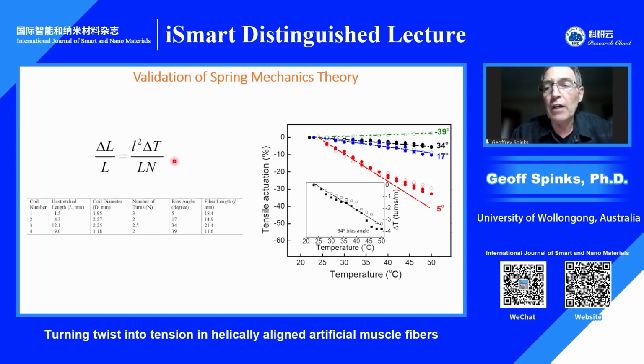And you can see there's really good agreement between the spring mechanics theory and the measured results. The only slight discrepancy occurs here at this small bias angle coil, where we're predicting more contraction than we're measuring. In fact, when we look closely at those samples, we could see at those temperatures that one turn of the coil was actually starting to touch the neighbor and impeding the amount of contraction that should occur in theory. So apart from that small explainable discrepancy, we could see that spring mechanics beautifully explained the actuation results in these twisted and coiled fibers. So we now knew the basic mechanism: the twisted and coiled tensile actuators were operating really as torsional actuators formed into coils. So all of the early work that we had done on torsional actuators was directly applicable to these twisted and coiled artificial muscles.